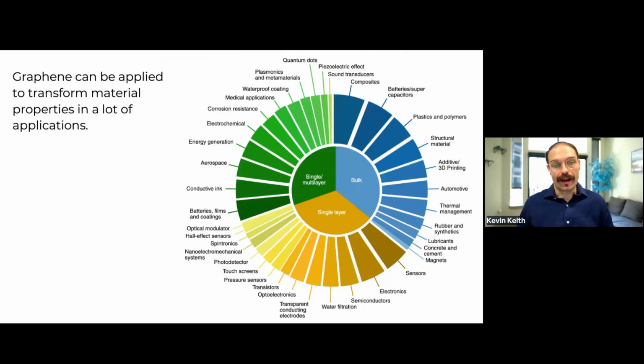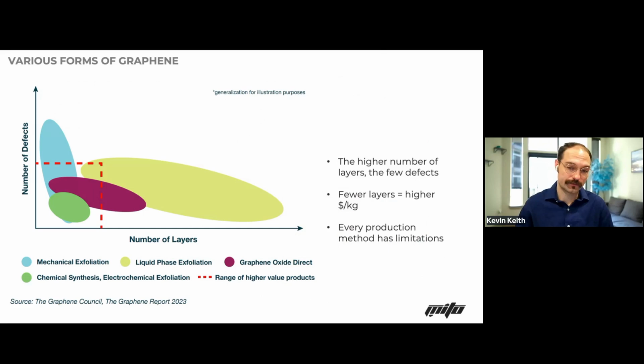And so graphene can be applied to a lot of different materials. Definitely not going to read all these, but it's broken up essentially into three different categories. You have single layer in the orange right here. You have single and multi-layers, so anywhere between 1 and 10 layers. 1 and 2 layers, and then bulk graphene, which is between 2 and 10 layers, that's considered bulk. This is only for graphene, not nanoplatelets or graphite. Graphite can go into batteries and supercapacitors. They are currently, but there's a lot of other intrinsic problems that I will not get into today whenever it comes to getting graphite into those battery anodes.